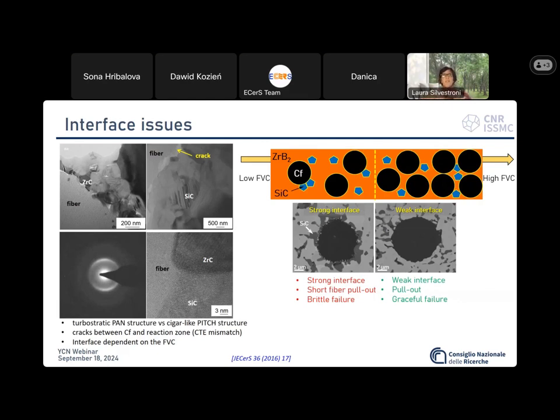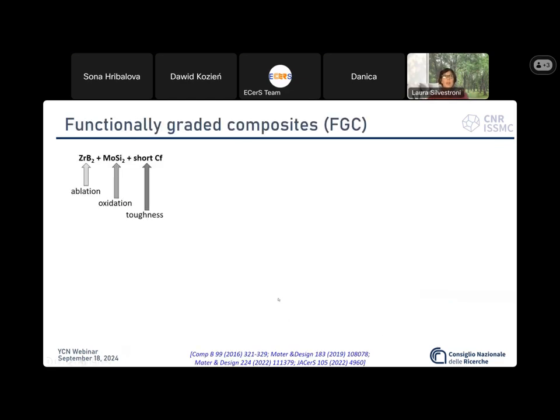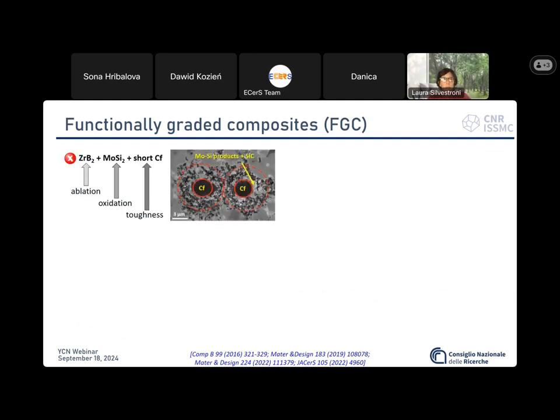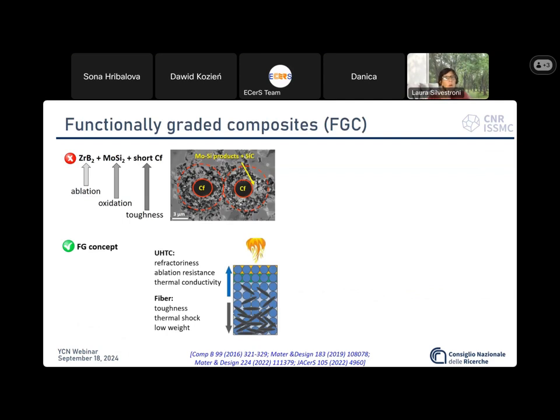In addition, the fiber, either silicon carbide or carbon, oxidize preferentially as compared to the boride refractory matrix. So to help with the simultaneous issues of fiber degeneration by interaction with the additive, efficacy of the fiber on the mechanical properties, and preferential oxidation, we have the smart and relatively simple approach of the functionally graded concept, where we can design a UHTC-rich outermost layer that protects from ablation, and a progressively fiber-rich core that provides failure tolerance and thermal shock resistance, besides making the composite overall much lighter.